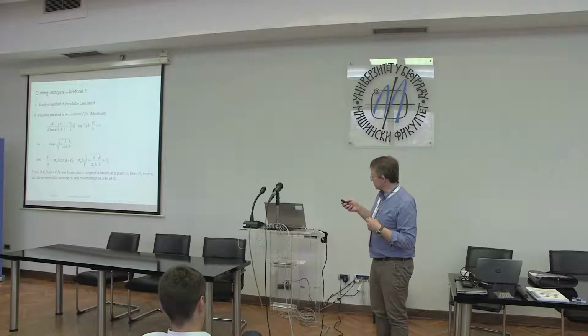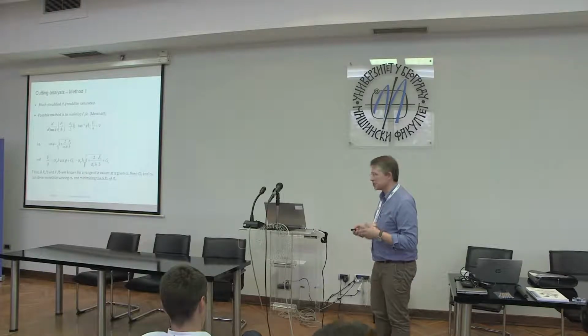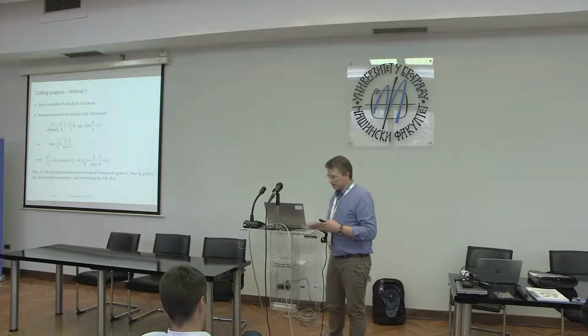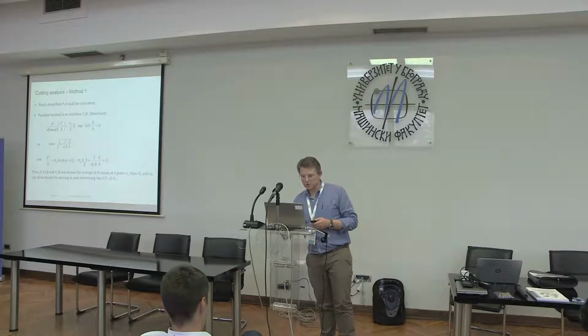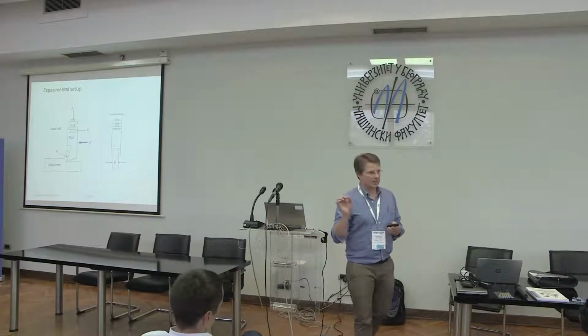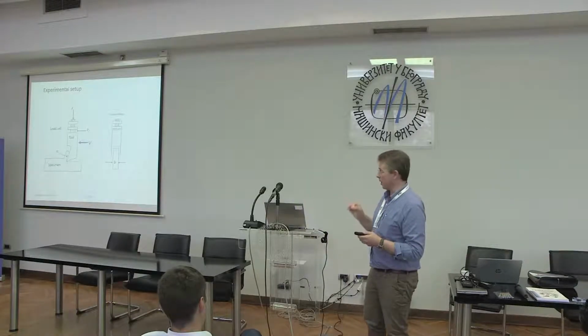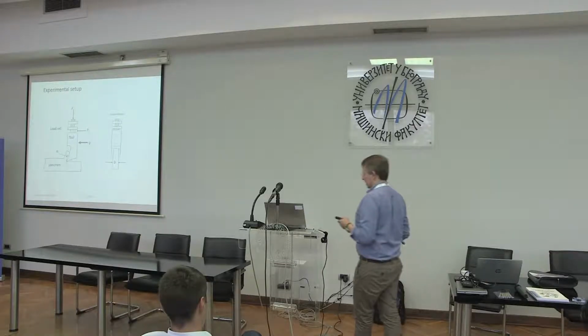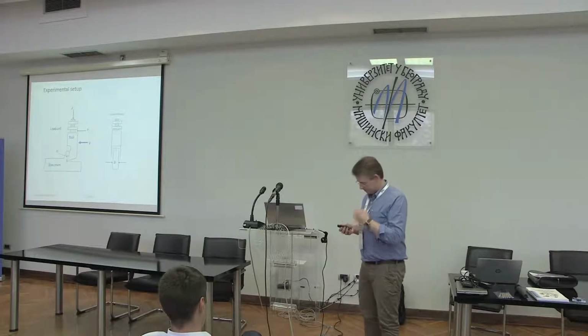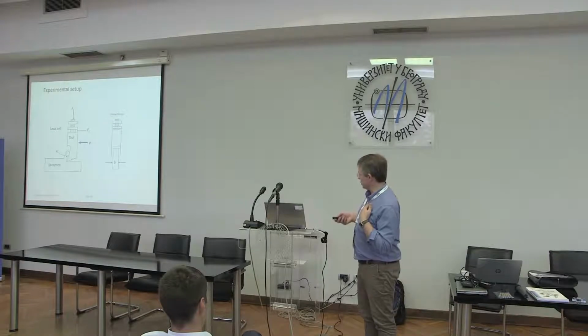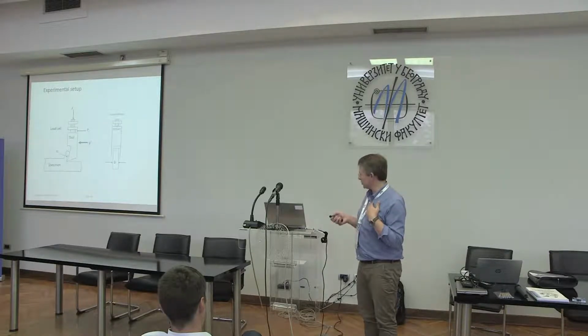So this was just to explain how the energy minimization process worked, leading to a different set of equations, but basically the fundamentals of the approach are the same, and what you're trying to do is get that intercept at the zero thickness. So in our experiment, briefly because time is short, we have our instrumented tool.